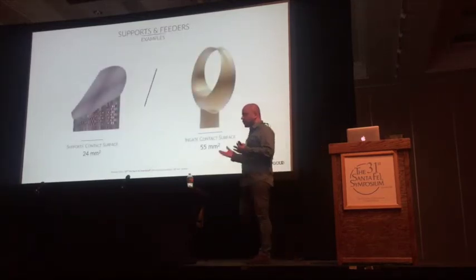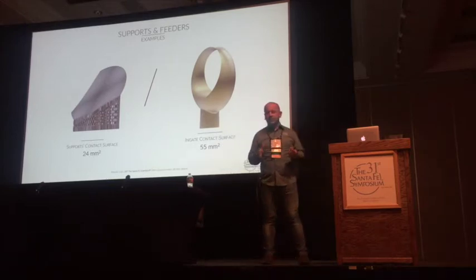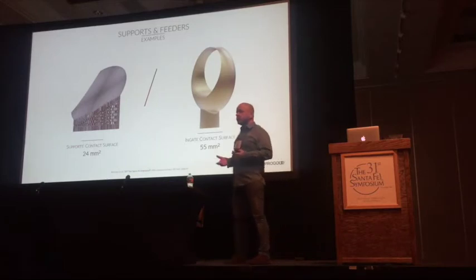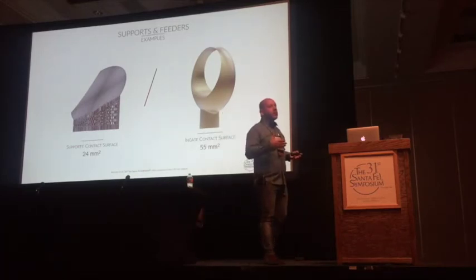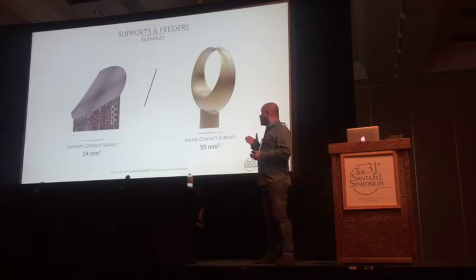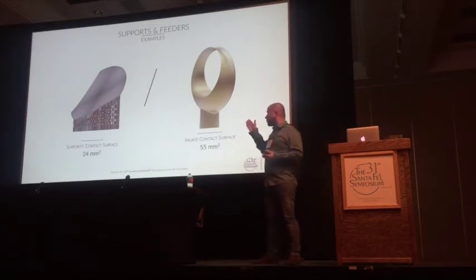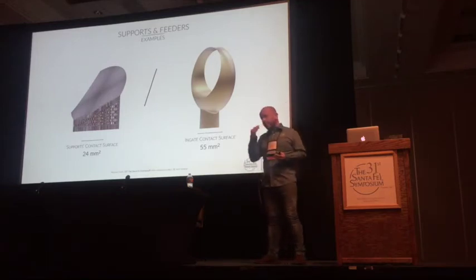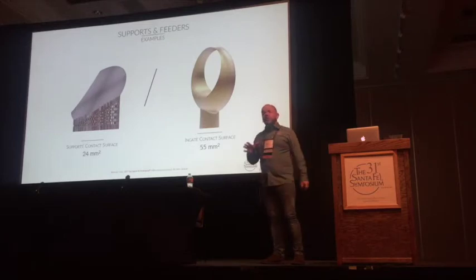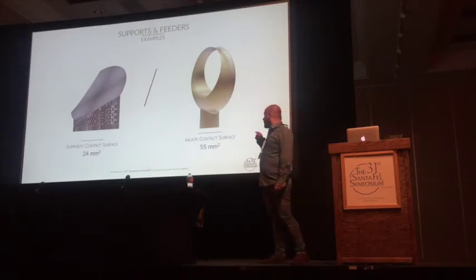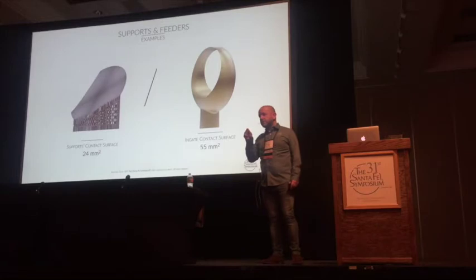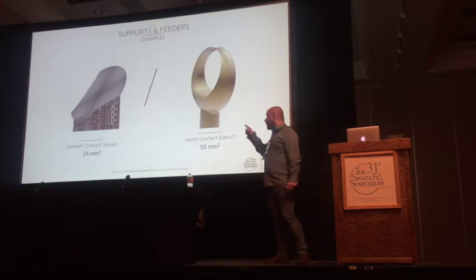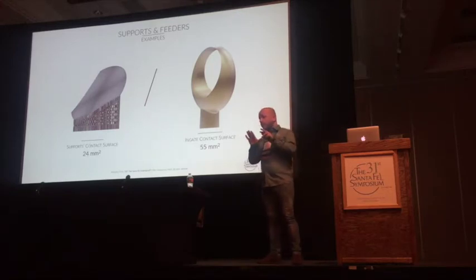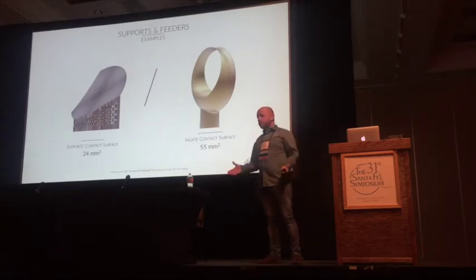And then in both processes, you have something that people don't like. In the case of casting, you have the feeders, so the sprues. In the case of 3D printing, you have the supports. In this picture, we show the same ring produced by 3D printing and by casting. The contact surface in 3D printing is much lower, and in casting it is something like double. In casting, the contact surface is equal to the total surface interested by the sprue. In 3D metal printing, we have a lower contact surface, but over a wider area.